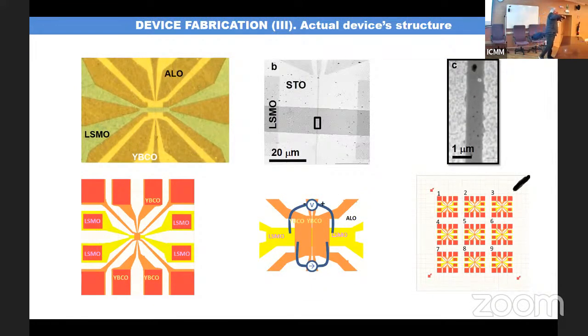YBCO growing on top of the alumina is a rock. It's amorphous and strongly insulating. And the YBCO growing in the trenches is epitaxial on top of the manganite wire below. So in this way, we grow these devices. This is the idea, right? The two superconductors with 1 micron separation on top of the manganite wire. And we grow several of these repeatedly on the same substrate.